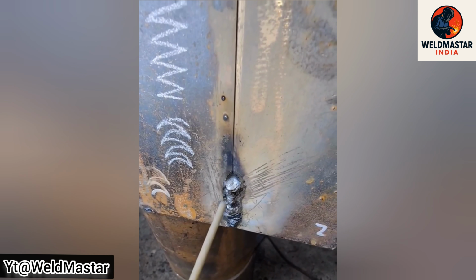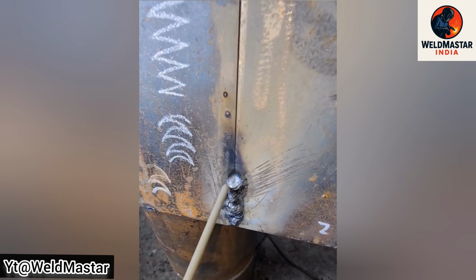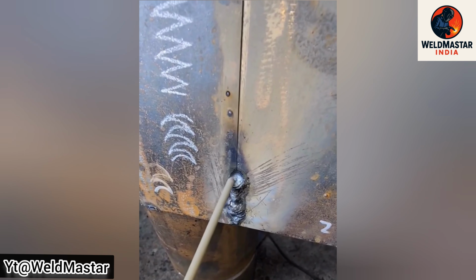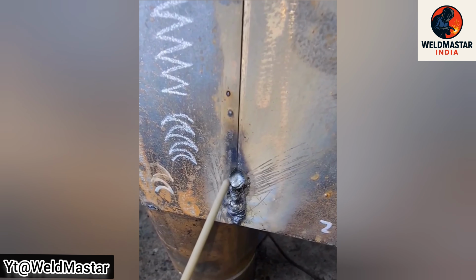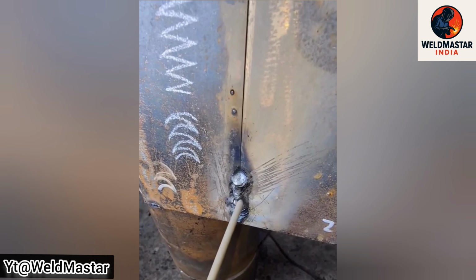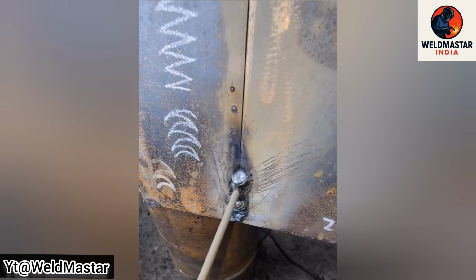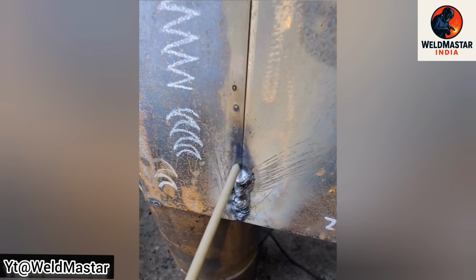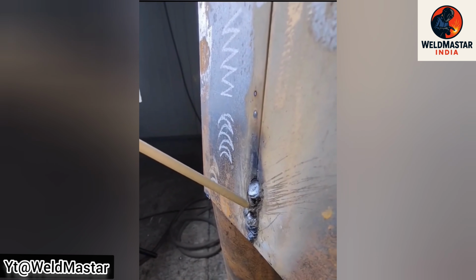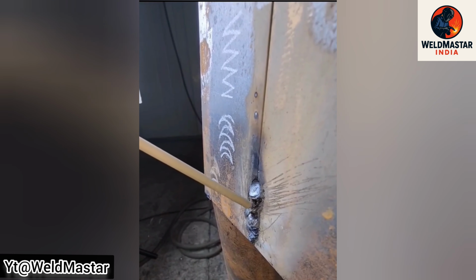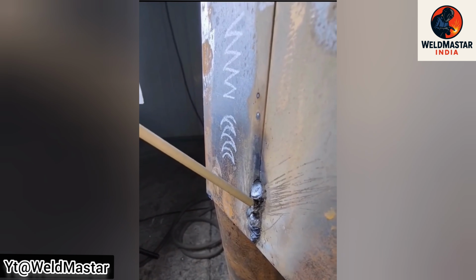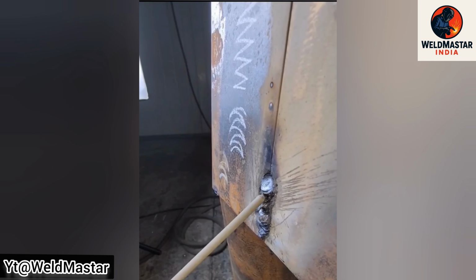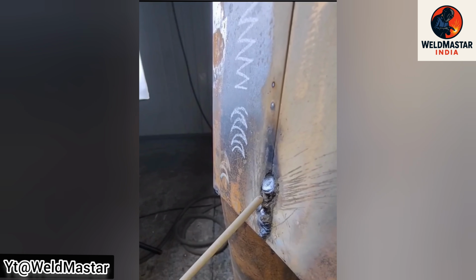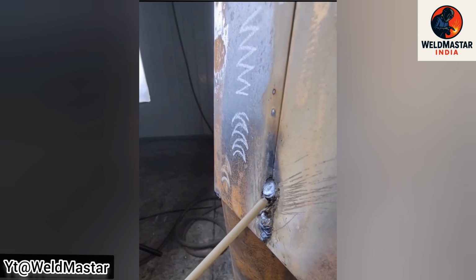The first cause is that the welding current is too high. The second cause is that the arc is too long. In other words, the electrode tip is too far from the base metal, so it can't hold the molten metal, causing it to sag. The third cause is that when swinging the electrode left and right, the middle motion is too slow and the sides don't pause to support the puddle. The fourth cause is an incorrect electrode angle. If your electrode is at the wrong angle, the molten metal will definitely sag.